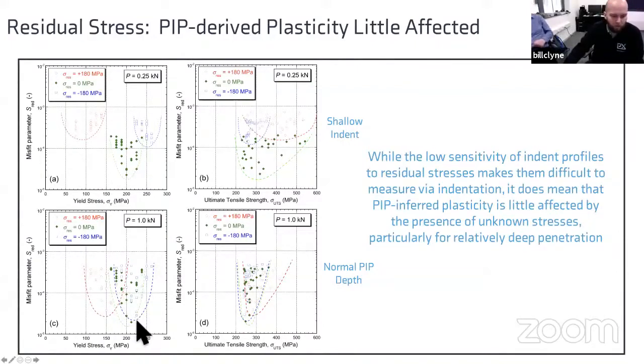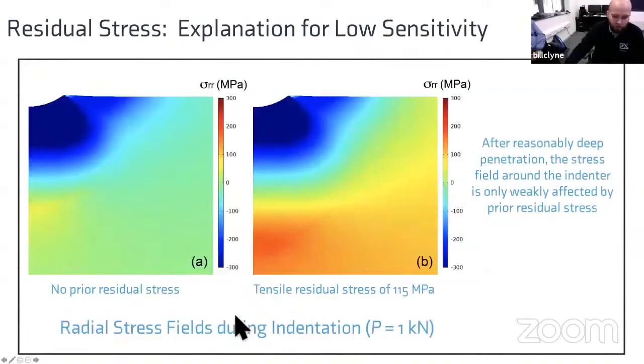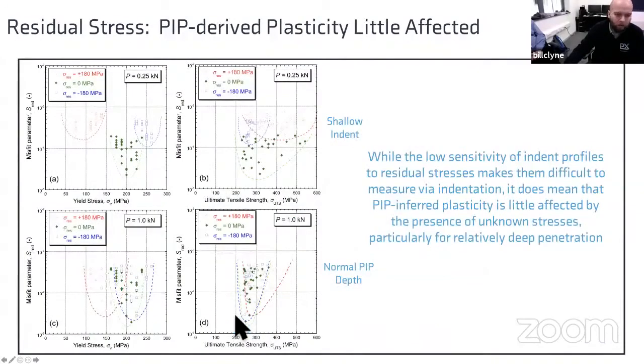So the compressive residual stresses will have a very small effect on the yield stress, and indeed the UTS at large penetrations. And the tensile residual stresses we can see have more of an effect on the yield stress, but almost no effect again on the UTS. So again, for relatively deep penetration, we can see that the effect of the residual stress is much less significant than at low penetrations.